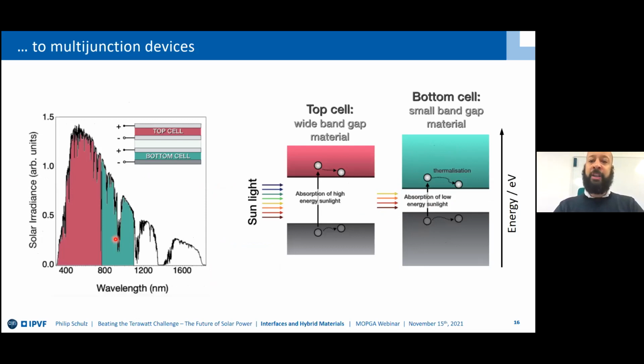Now, if we look at the tandem device, it's a little bit different. On the left-hand side, you see this configuration with the bottom cell and the top cell. The top cell has a higher band gap, so it absorbs light at higher energies. So it has very small thermalization losses for these electrons, but sunlight of lower energies will go through and will then be absorbed in the bottom cell. Over here, this part of the spectrum, again with small thermalization losses. So with each cell you effectively reduce the amount of thermalization losses that you accrue.